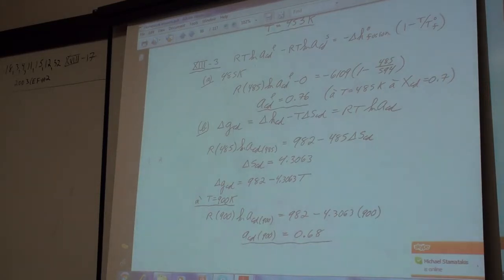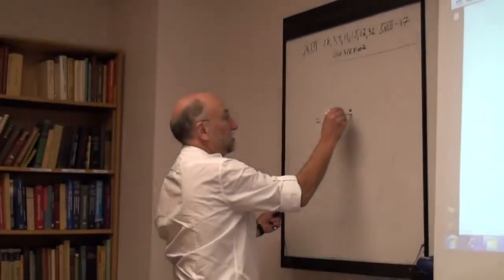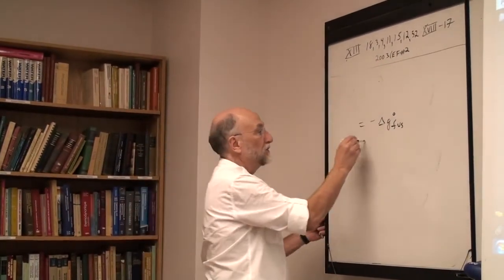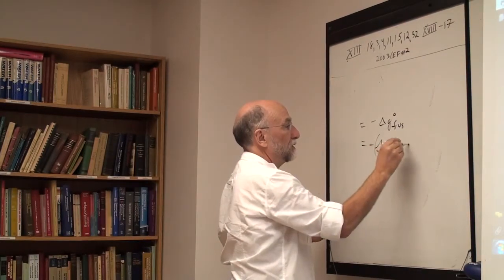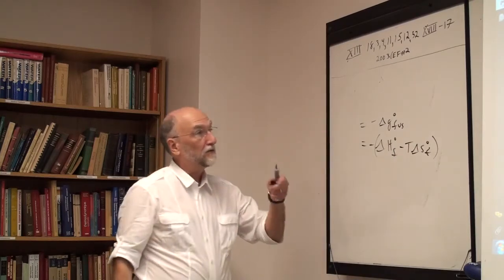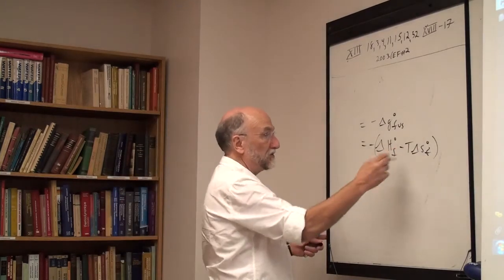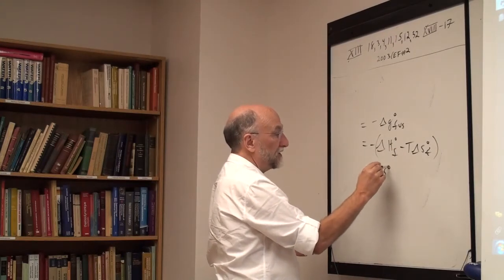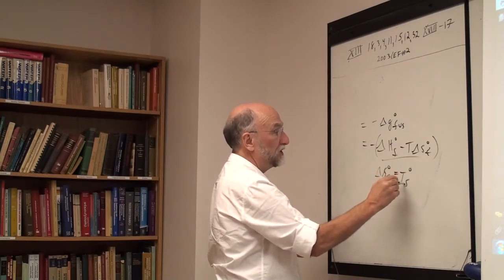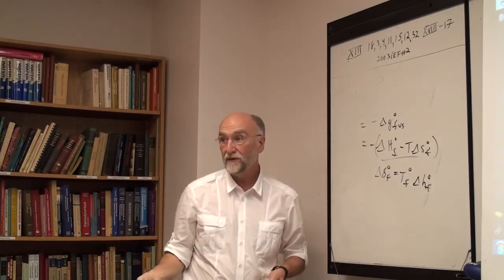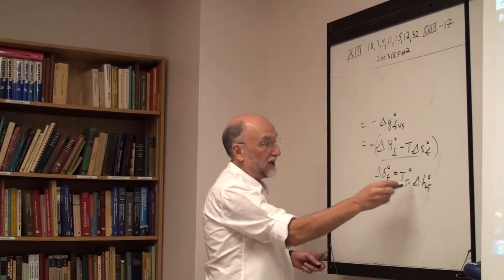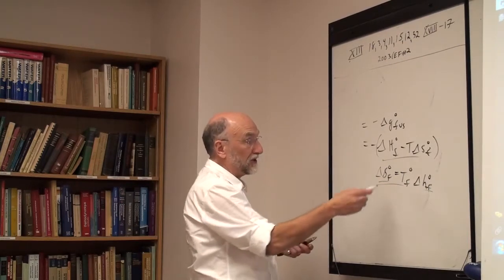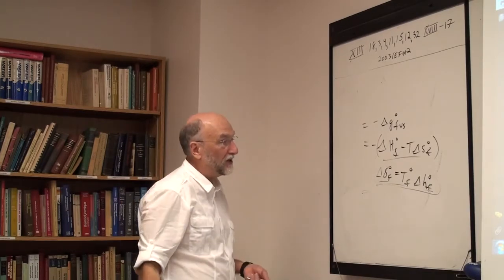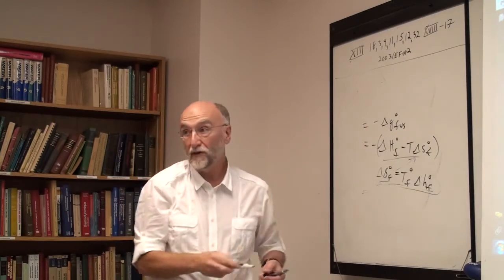Well, the right-hand side of this equation is actually equal to minus delta G of fusion, which is equal to minus delta H of fusion minus T delta S of fusion. If we assume that the heat of fusion is constant with temperature, then we get the delta S of fusion. Delta S of fusion is delta H of fusion at the melting point divided by T fusion, because at the melting point delta G of fusion is 0. This is only true strictly at the melting point, but if delta H and delta S are independent of temperature, then you can substitute that back in here and you end up with that equation.